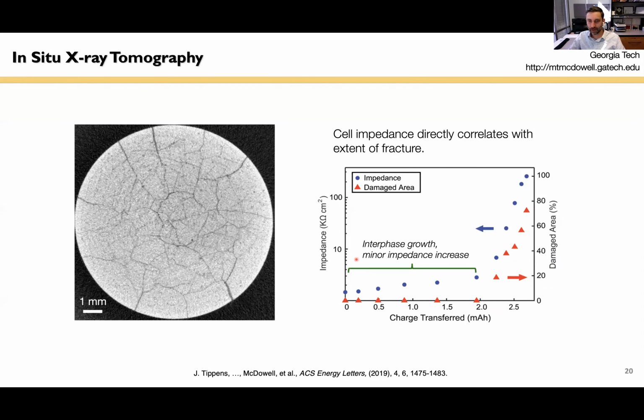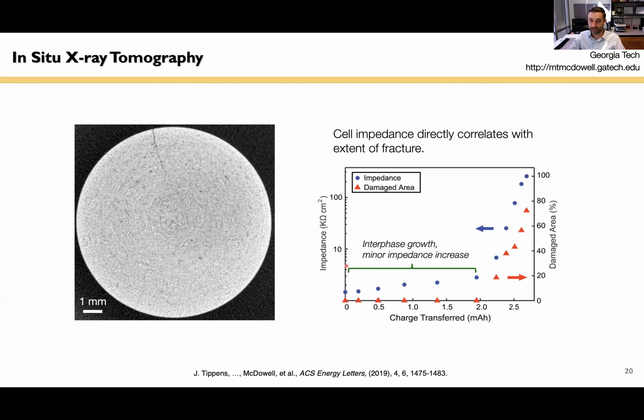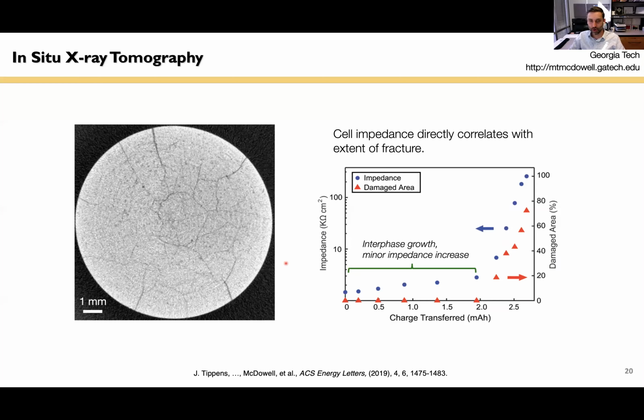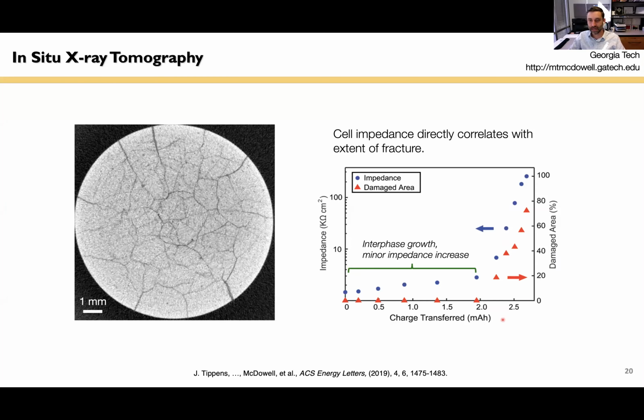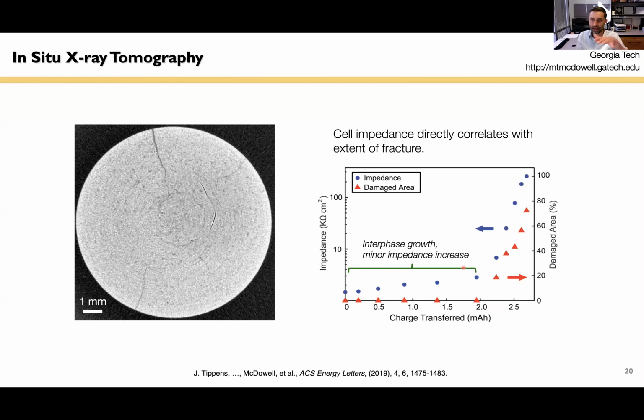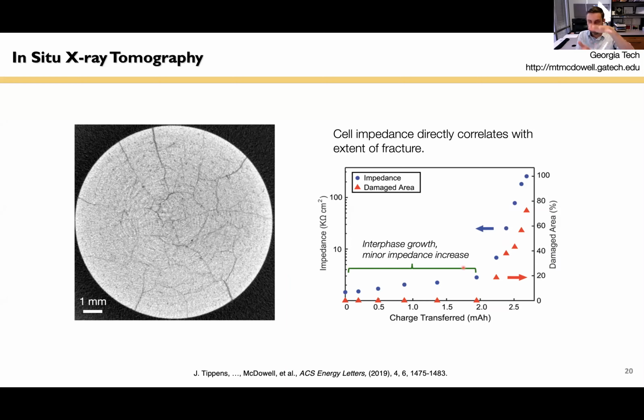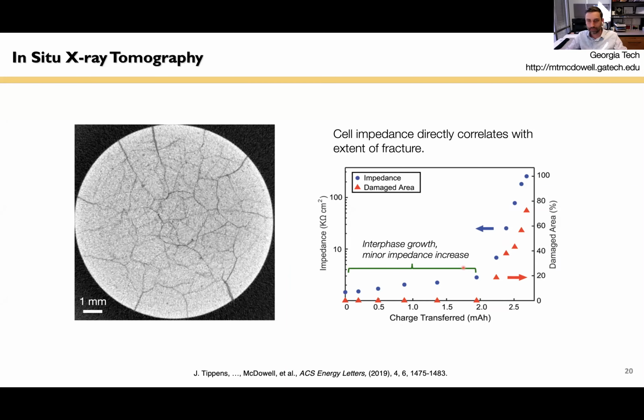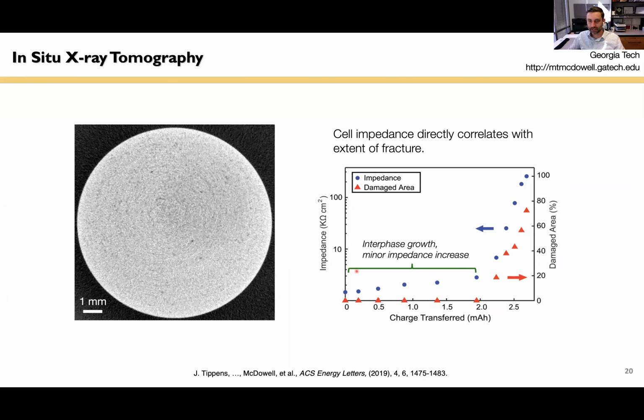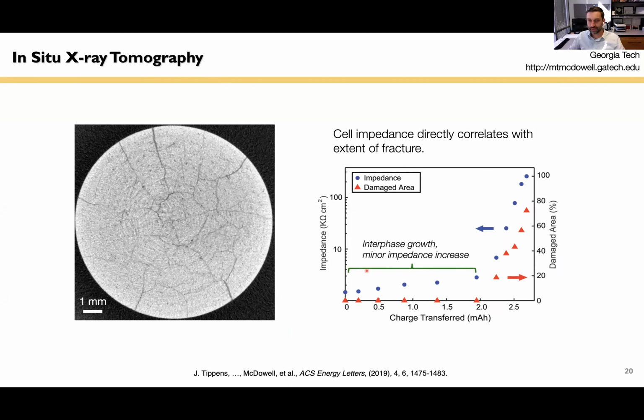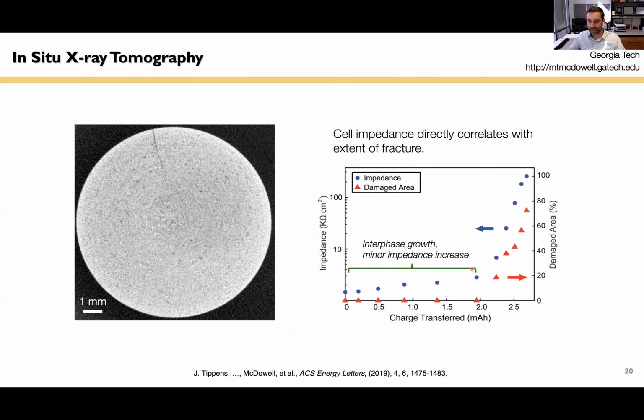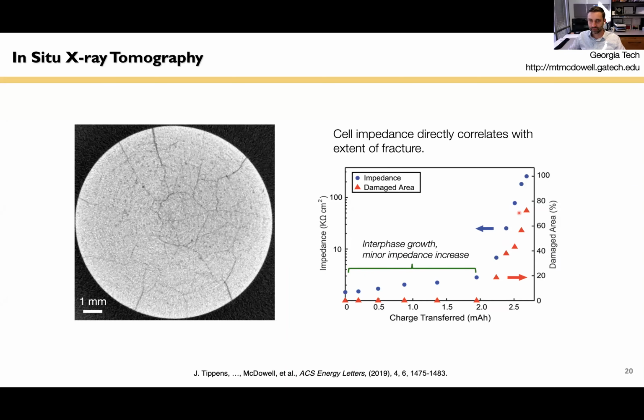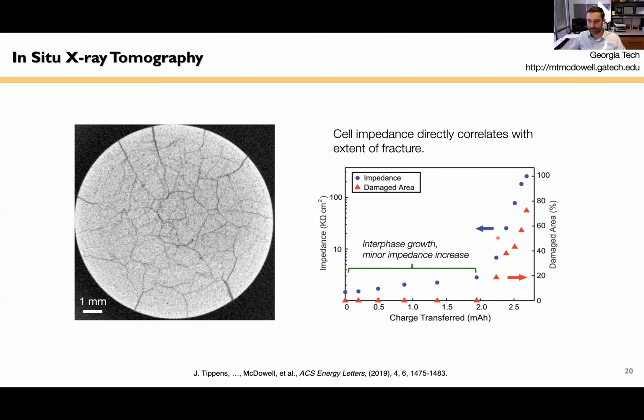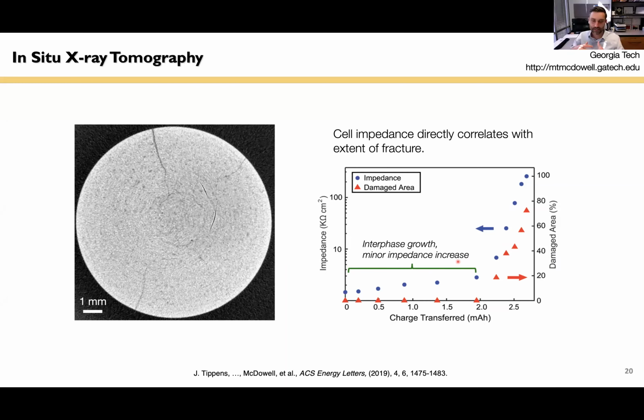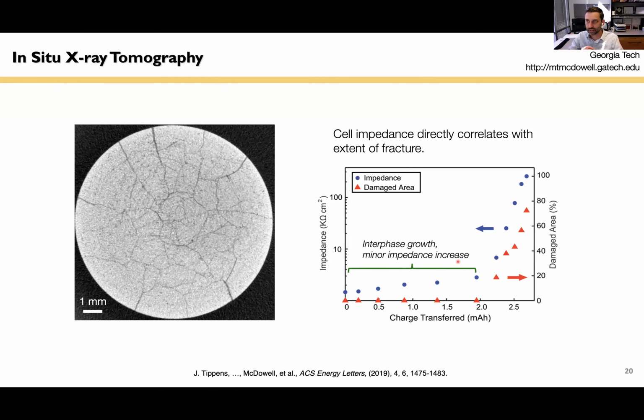What we found through these experiments is that, well, what we know is that interphase is growing on the top and bottom interfaces here the entire time during these experiments. So we have the formation of these new phases at the interface on the top and bottom. But during interphase growth, there's really very negligible impedance increases. It's not until we start getting fracture where our cell fails and our impedance increases substantially. So we learned that actually the interphase itself is not really causing electrochemical failure here. Instead, it's the fracture process.